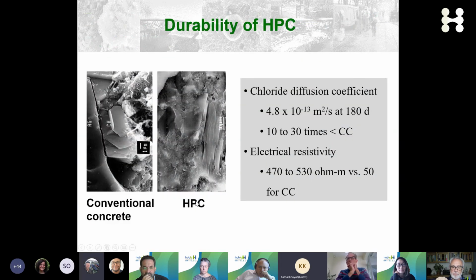Now you can reach 100 years by using high performance concrete that can give you very, very high corrosion resistance. You could see here the chloride diffusion coefficient is about 10 times less than that of conventional concrete, and the electrical resistivity is also about 10 times greater than that of conventional concrete. So the service life is not 35, it's 100, and now we're even designing for 125 plus.